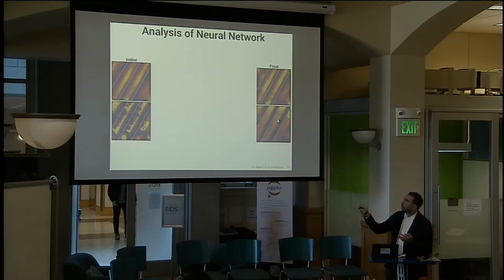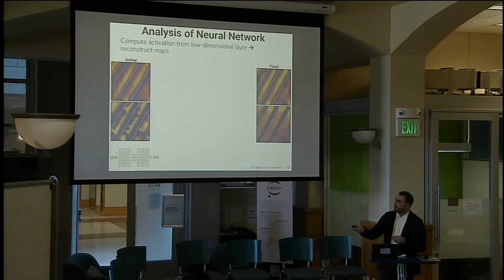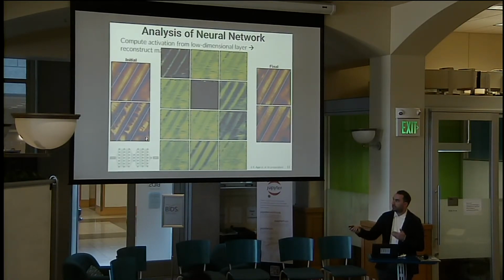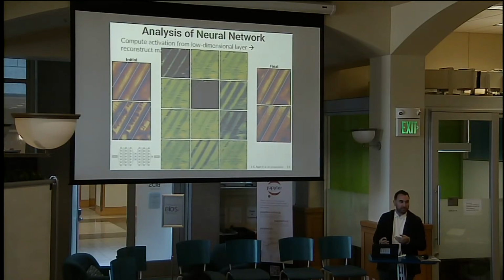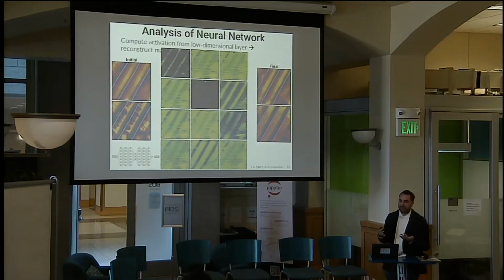If you do this, and these are the static images of the actual structure, which was taken before and after this event, and you train this autoencoder and then output that low-dimensional representation, we didn't provide it with any of the pixel positions. So if we reconstruct these maps from just analyzing the spectra, and the maps reflect the original structure that we know exists in the material, we have, as a first pass, a validation that we're actually learning something interesting.